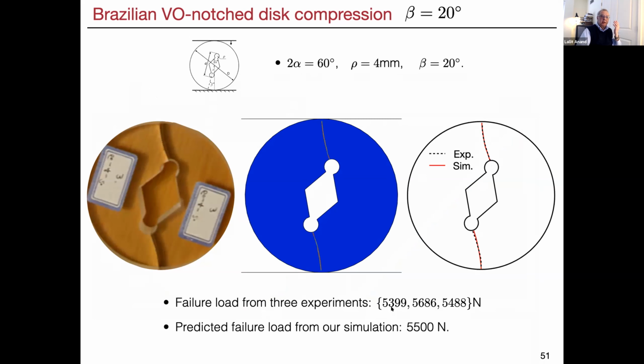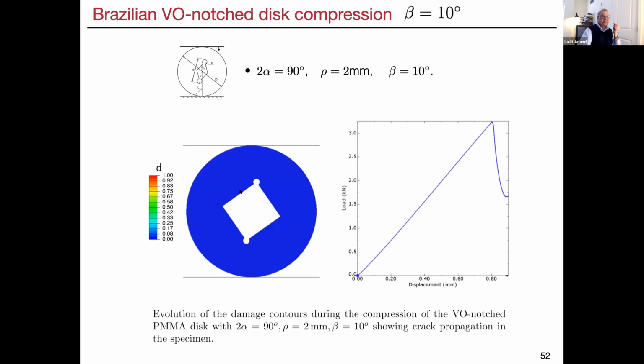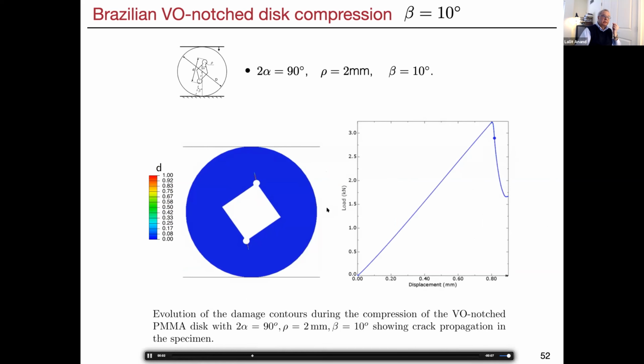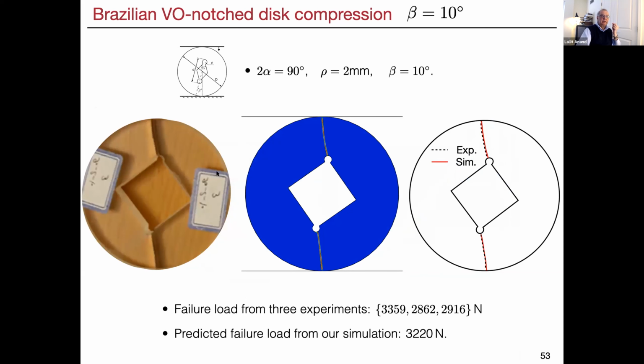In addition, from the experiments, they did 3 experiments. They got about 5.4 kilonewtons as a failure load, and the numerics predicts about 5.5 kilonewtons. That's pretty encouraging. So that's one geometry. Here's another geometry, a different angle. Now 2 alpha is 90 degrees, different root radius, different angle. Again, you can do the simulation, so it'll predict the path and the load drop. That's the actual load. And again, this is their specimen. You can overlay the simulation and their specimen, and it looks pretty darn good. And the loads are also predicted to be in the range of 3.2 kilonewtons.